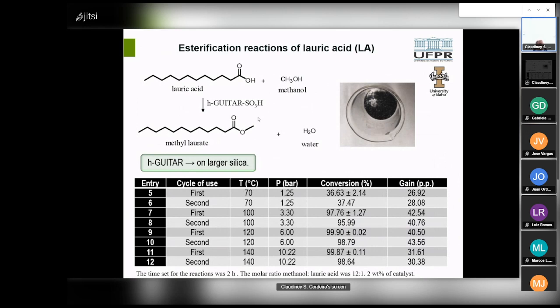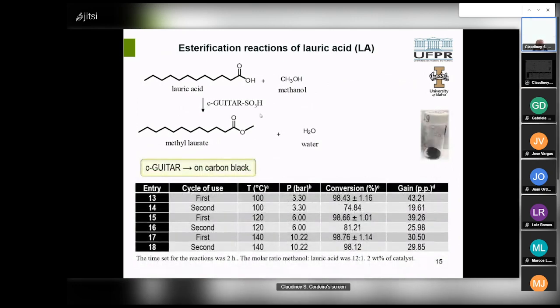The sulfonated graphene used was supported on larger silica. These are the results obtained using guitar on carbon black. The results for the first use are statistically similar to the previous one. However, there was a loss of activity during the second use.